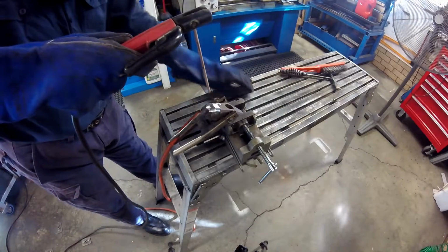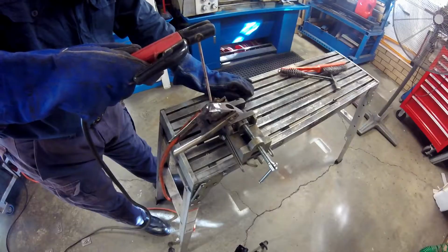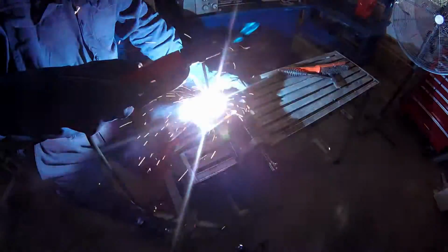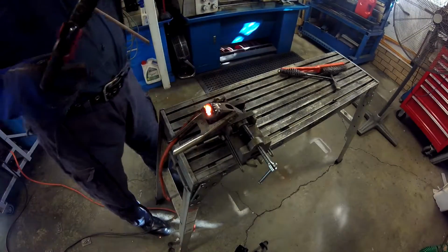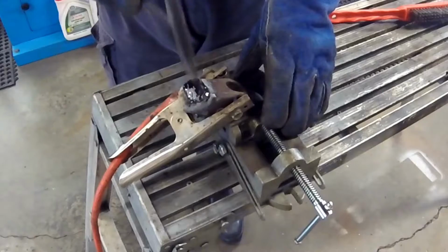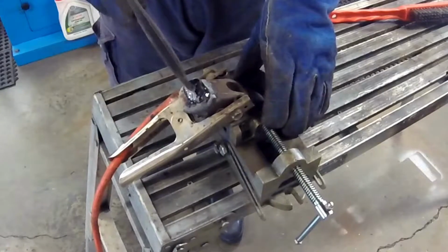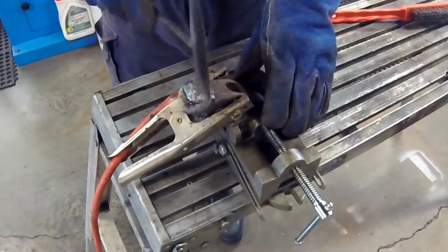I am doing this weld repair with a specialist repair electrode. It is a low hydrogen, high strength electrode, but in reality probably any 70-18 or 70-16 electrode would do just as well. The welding here is pretty straightforward, laying down a succession of overlapping beads until the level of the weld metal is above that of the original hammer surface. Yes, a bit of imagination is required to visualise where that actual surface is.